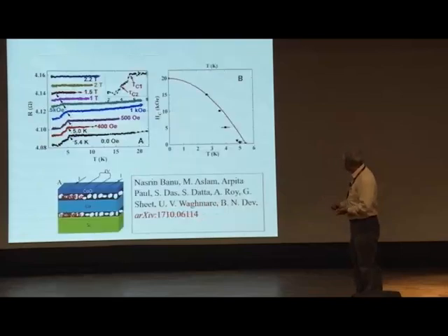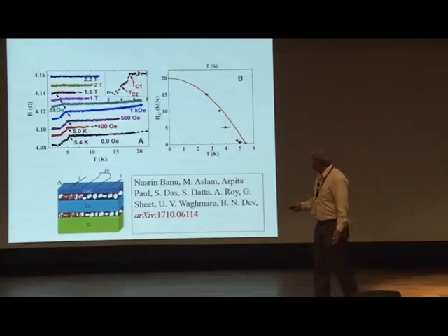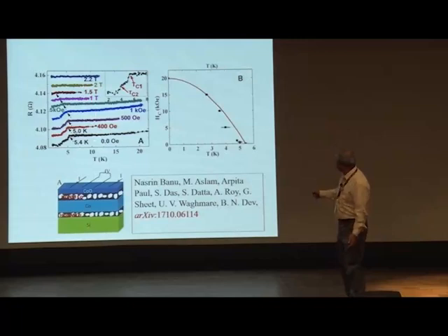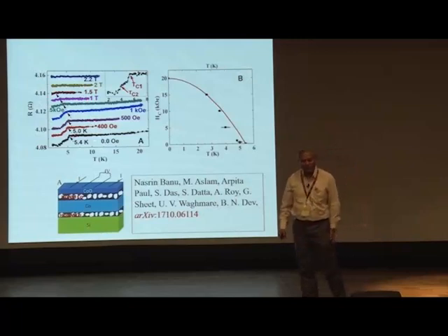So now for the sample, this is at zero field. We have 2 transitions, 5.4 K, which is blown up here, and 3.7 K. The 3.7 K is coming from indium. This 5.4 K is coming from our cobalt sample. And as you apply an increasing magnetic field, you see this transition temperature shifting. Again, it's a definite indication of superconductivity.